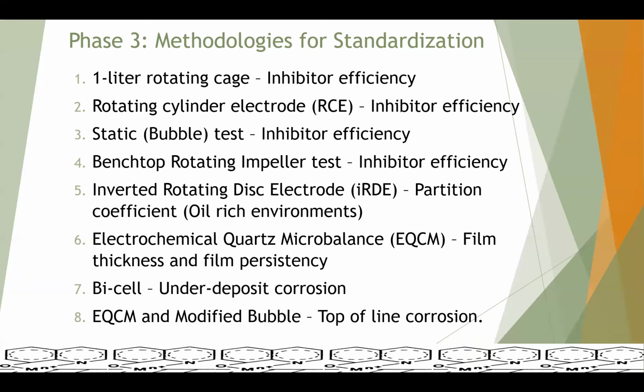Top-of-the-line corrosion has become an important failure mechanism in some parts of the world, especially in wet gas transmission pipelines. And we believe that one of the methodologies, EQCM or modified bubble test, can be used to evaluate the efficiency of corrosion inhibitors for the top-of-the-line corrosion. So in total, we'll be standardizing 8 methodologies in phase 3.